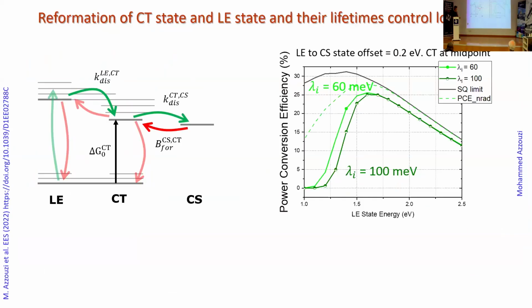So for example, we could now revise our map of power conversion efficiency as a function of band gap and look at it as a function of some parameters controlling this competition of both what happens at the interface and what happens in the device. And for example, we find that if we were to change the lifetime of the photoexcited state, if we make that longer by reducing the high frequency reorganization energy for the exciton, that allows higher power conversion efficiencies to be reached at a smaller band gap. So that's a good thing.